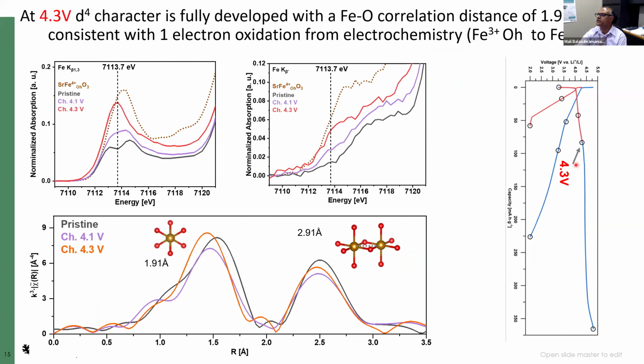Now, as you go further to 4.3 volts, this intensity increases, and there is more increase in intensity here. So we believe that the d4 character is fully developed, and the iron-oxygen correlation distance comes down all the way to 1.91 angstrom. This is consistent with the one-electron oxidation that is expected for this chemistry, and is consistent with Coulomb counting that one can do while performing the electrochemistry.